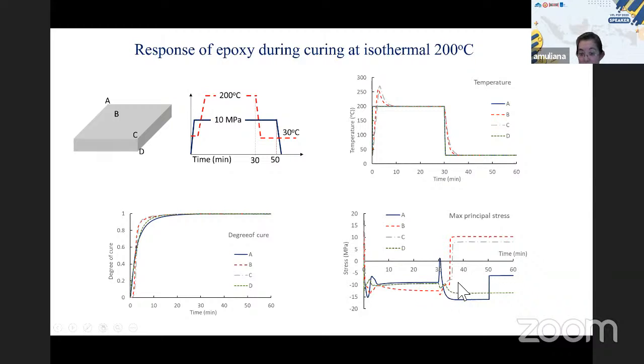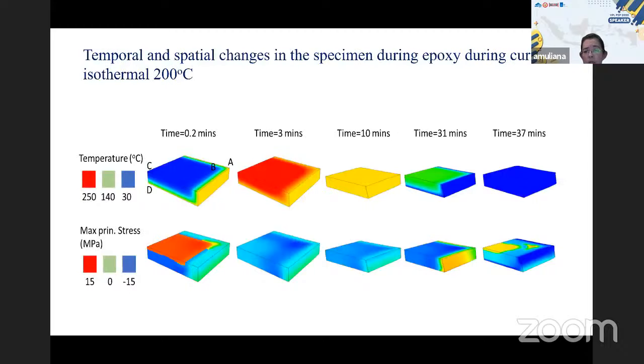When it's cured, there is also shrinkage. So now when you bring it down to room temperature, right, you'll see another change in stress. And in the end, you'll see what we call the residual stress. When it is high enough, it might induce a defect or damage in the composite or in the polymer. One thing that I also mentioned, curing is exothermic, it generates heat, right? So now you say, okay, my cure temperature is 200, but because of this exothermic process, it can go much higher than that. So all of this will affect the response of the cured polymer. Just to show you how the space and time change, this is the contour of the temperature and stress, right? So in the beginning, the temperature is still increasing.